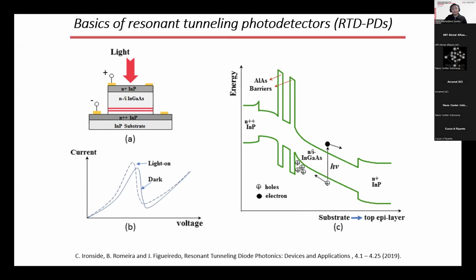However, things become really interesting when you have light shining on your device, because now you have photo-generated electrons here and photo-generated holes in here, and then the electric field would sweep your carriers. For electrons, it would sweep quite easily in this device, but holes will get stuck in here because they accumulate in these barrier structures. And this gives an enhancement in the electric field, because as they accumulate, the built-in potential in this region increases. Effectively, this makes the resonance be achieved at a lower voltage.